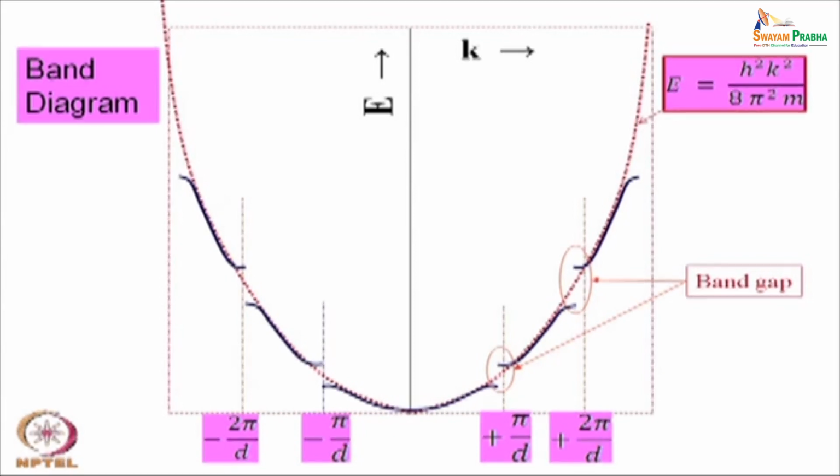The k values actually relate to the crystallographic planes in the reciprocal lattice, and from that one can see that the slices you see here are actually not planes but cylindrical surfaces, basically complex 3 dimensional figures. These regions where continuous or quasi continuous energy levels are available are called zones, and a particular name has been given to them: Brillouin zones.